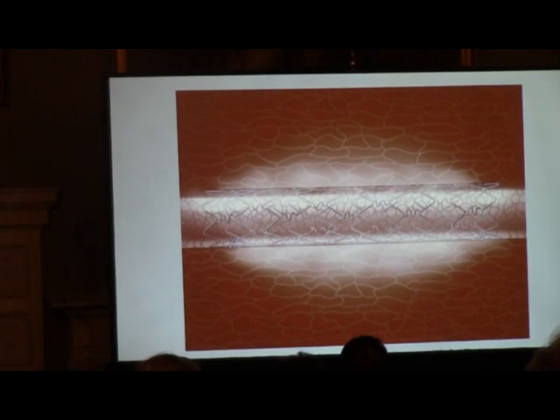Well, you may know, if you put a regular, what are called bare metal stent in, often it causes a problem called restenosis. You get smooth muscle cell proliferation, the patient could die at minimum, you'll have to reoperate. It happens about 50% of the time. So now what they do is you take Taxol, another anti-cancer drug, not unlike BCNU in some ways. You take that, but because you coat it onto the stent, you're delivering it locally. So you get away with 1/1000th the dose that you would if you do it clinically. And clinically, if you took 1,000 doses, you kill somebody. But locally, it works. It prevents the smooth muscle cell proliferation. Millions of these are used every year.